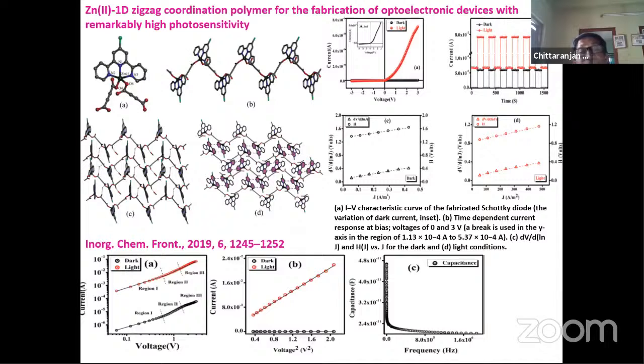Okay, the same type of system. This is a zinc complex, but the difference is that herein we use the terpyridyl blocker with the carboxylate bridging system. Zinc terpyridyl blocker: the terpyridine has a huge number of pi electrons and the molecule is also pi acidic. So we expect better conductivity, and we also observe the conductivity.